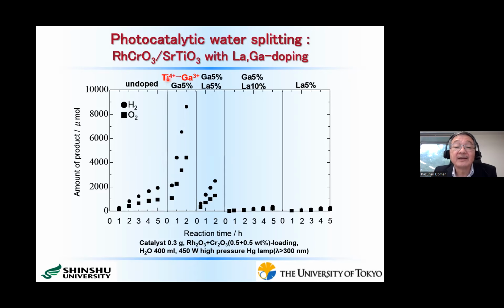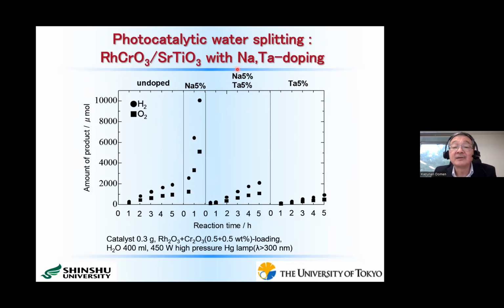Then when we replace the titanium 4+ cations by lower valent gallium 3+ cations, as you see, the water splitting activity was enhanced. On the other hand, when we replace the A site strontium 2+ cation by the higher valent lanthanum 3+ cation, activity was almost lost. A similar tendency was observed using different combinations. In this case, we used sodium 1+ cations to replace the A site cation and tantalum 5+ cations to replace the B site cations. And this is again the reference activity. Then if we replace the A site strontium 2+ by sodium 1+, we get better activity. However, if we replace the B site titanium 4+ by tantalum 5+, the activity decreases.